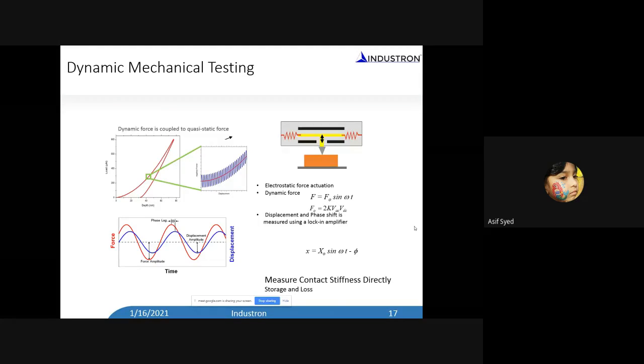Now I'm going to use it on polymer materials. Instead of applying a static, quasi-static force and measuring the load displacement response, I can also superimpose a dynamic force, a sinusoidal force, and measure the sinusoidal displacement response. For example, if I apply a sinusoidal force at a given frequency using a lock-in technique, and I only look for the displacement response at the same frequency, I can measure the displacement amplitude, and I know the force amplitude applied. If I take the force amplitude over the displacement amplitude, it gives me directly the stiffness of this contact. And if I do it on a polymer material, I can directly understand the storage and loss components of these viscoelastic polymer materials.